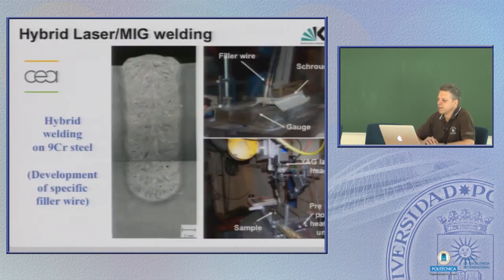And this was transferred to Eurofer, and you see such a hybrid laser welding, or whatever they name it, seems to work quite well. Here are the several weld layers which have to be brought up in various steps, and the depth of this weld is almost 20 millimeters or so. So in principle it could be applied also to these 40 millimeter deep welds.